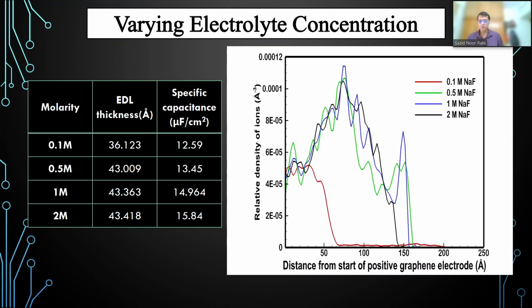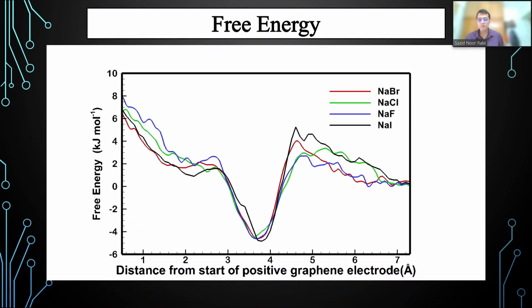We have also varied the molarity of the electrolyte, and we can see its effect here. The EDL thickness increases with molarity, and the specific capacitance also increases with molarity, which is actually not consistent with previous comparisons we have seen. This is probably due to the increased amount of cations and anions compared to the water molecules, which have remained fixed in this case.